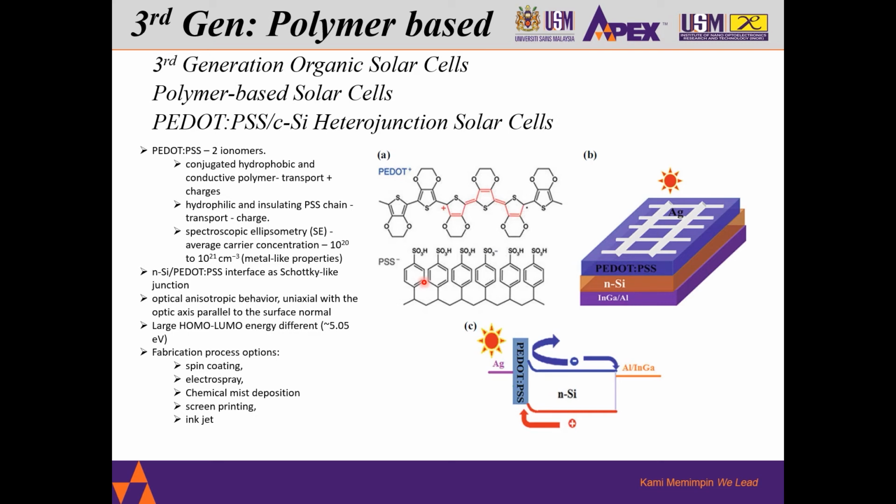Based on spectroscopic ellipsometry, it is revealed that the average carrier concentration for this modified PEDOT:PSS is 10 to the power of 20 to 21 per cubic centimeter.